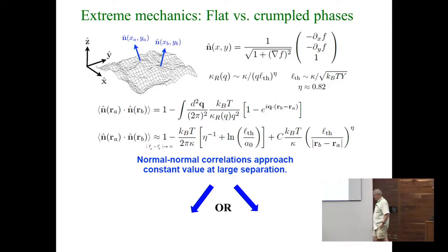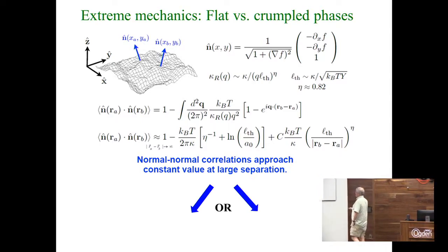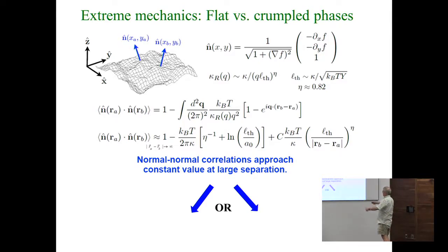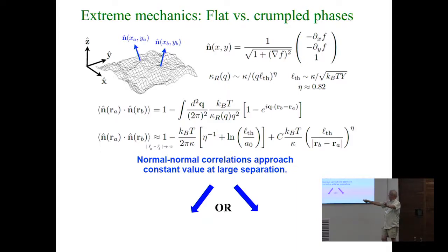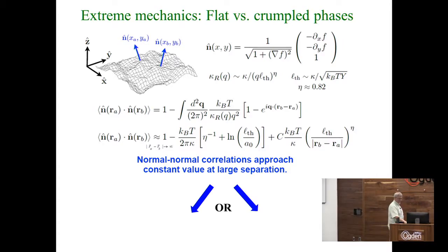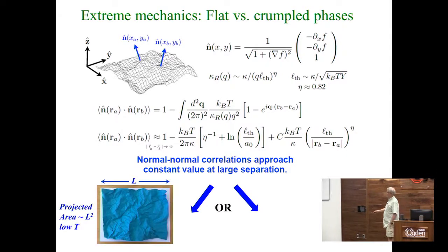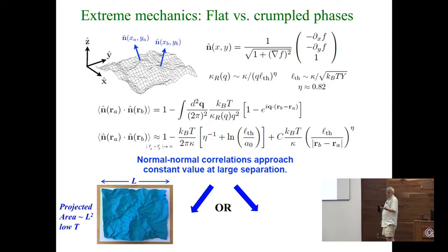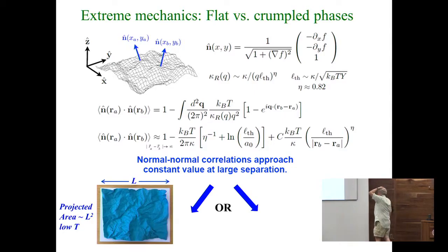In fact, that's the kind of thing that Mike Kosterlitz might have talked about earlier in this week. In any event, as I take the normals further and further apart, I can work out this normal-normal correlation function. It goes to a constant at low temperatures. Here's how it goes to that constant with this power law. And then there's this suppression relative to 1. If we're perfectly flat, this correlation function would be 1 at large distances. It's suppressed, and at low temperatures, when kBT over 2 pi kappa is small, this presumably is a description of the correlations in the flat phase. And that's what I've been talking about for most of this lecture.